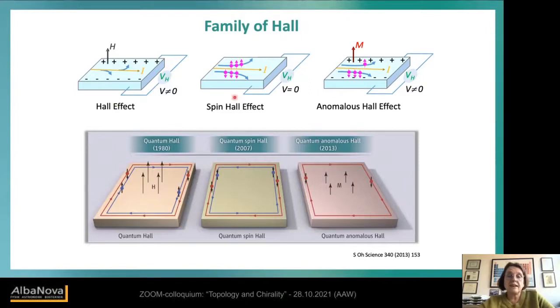And all of these quantum effects have their simple classical counterparts, and most of our measurements play a role here, because most of the time the measurement of the quantum Hall effect is exactly the same as the measurement of the Hall effect. So simply to show you, you might be a theoretician, what we do is more or less we take our crystal, which you already saw, and we put it in a machine, we cool it down, we measure the transport here, and eventually we apply a magnetic field. And this is a Hall effect, and if we have magnetic materials, we have this intrinsic magnetic material, but today I focus more on the non-magnetic material.